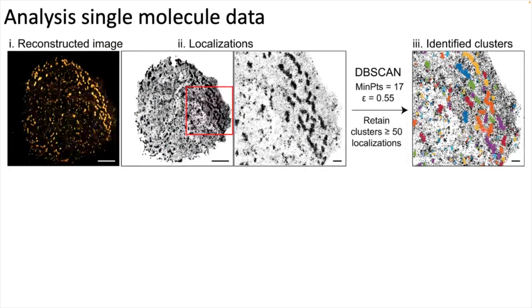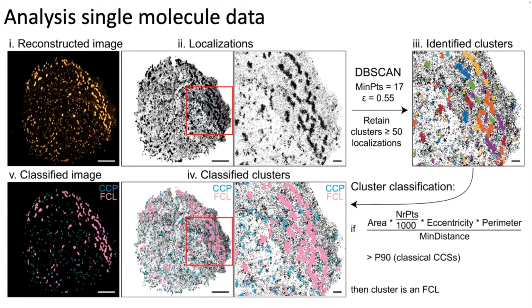And then what we did after was saying, okay, if we assume that clusters that have a very big area, a lot of molecules that are not spherical, that are a little bit elongated and have a long perimeter and are close to each other, we say, okay, those are a flat clathrin lattice. So these extensive structures. And then we can look back to the image, and to each cluster that was identified, we can say, okay, these ones are the pits, the spherical clathrin structures that are detected in endocytosis, and then you have the pink ones that are these extensive clathrin lattices.